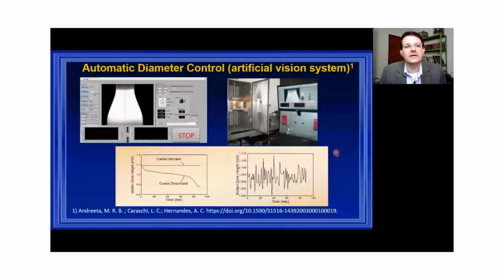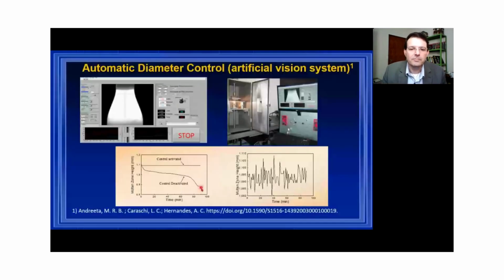And we have automatic diameter control. It's an artificial vision system, and we can look at the molten zone and compare and try to stabilize its parameters. So here you can see when the control is activated, the diameter is almost constant. And when it's deactivated, of course, because of the laser fluctuations and other factors, such as growing crystal, you need more power. You have a diameter that fluctuates along its growth, okay?